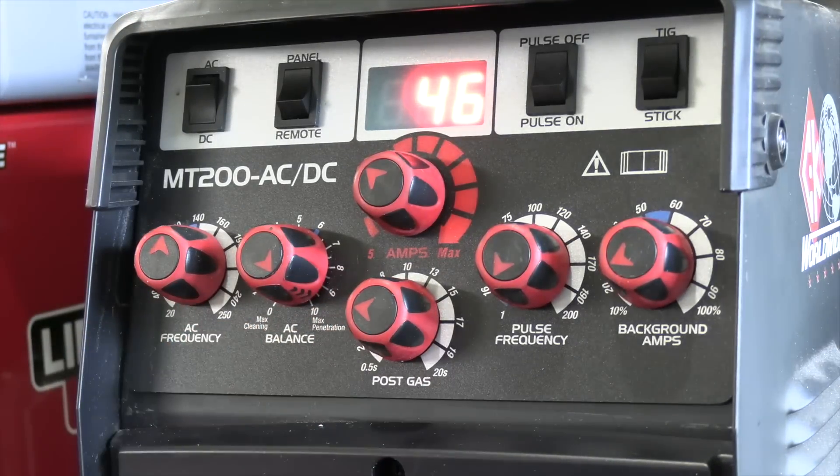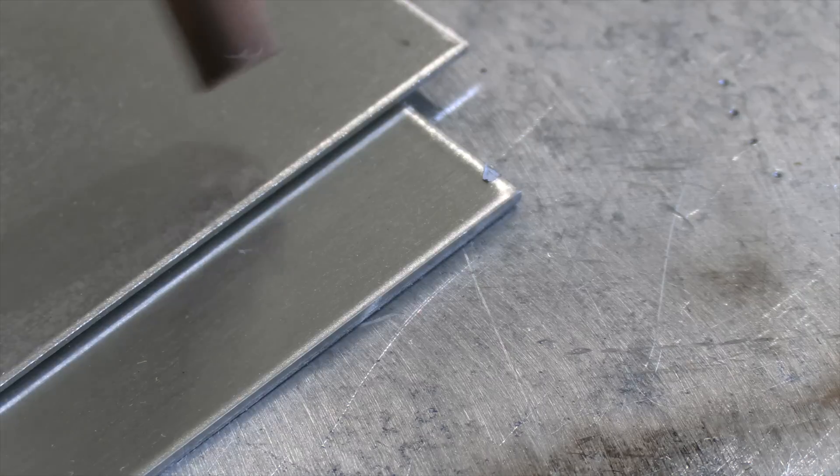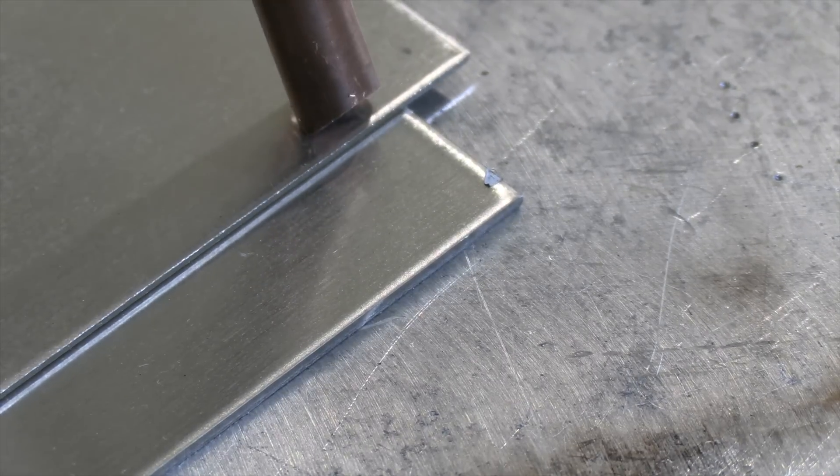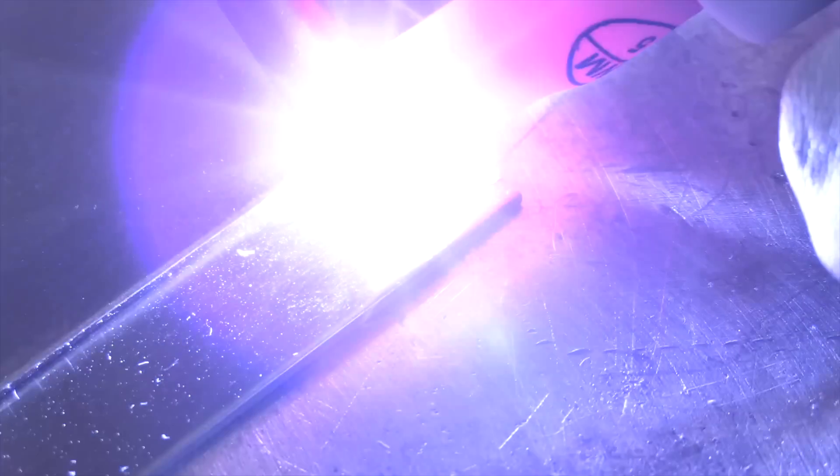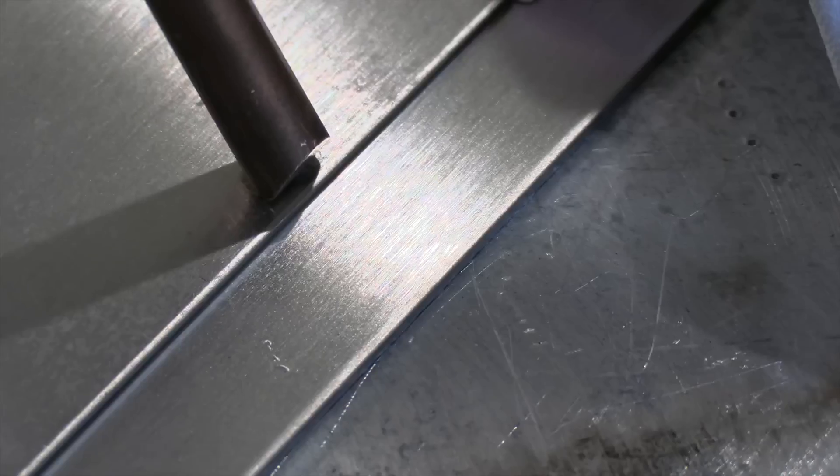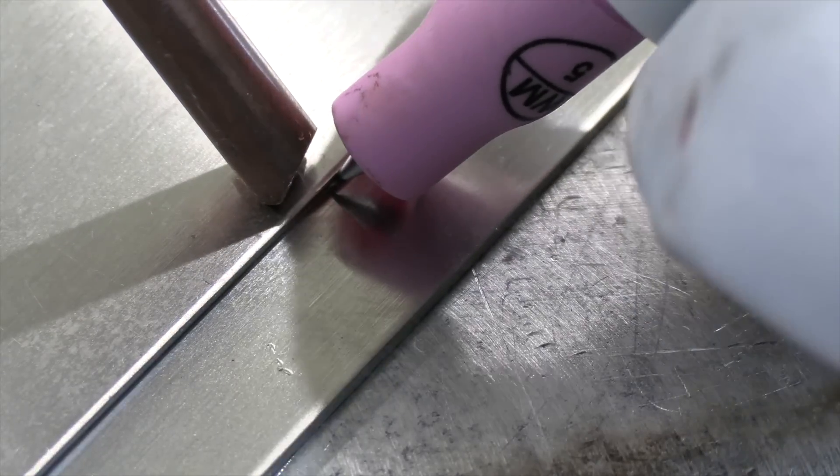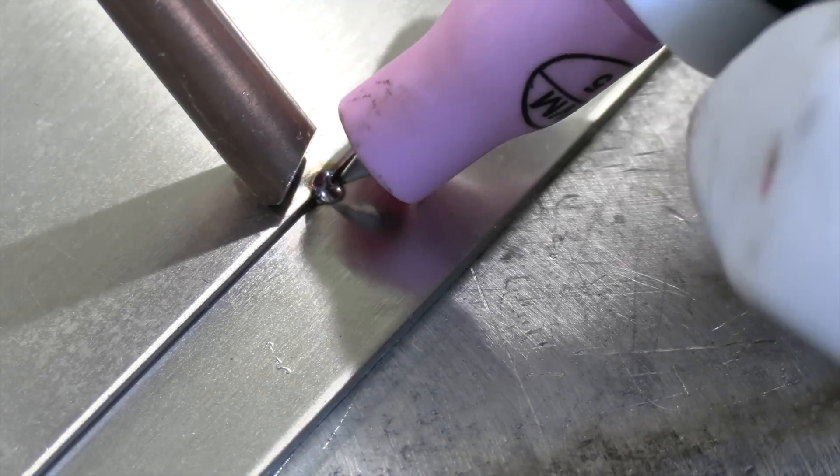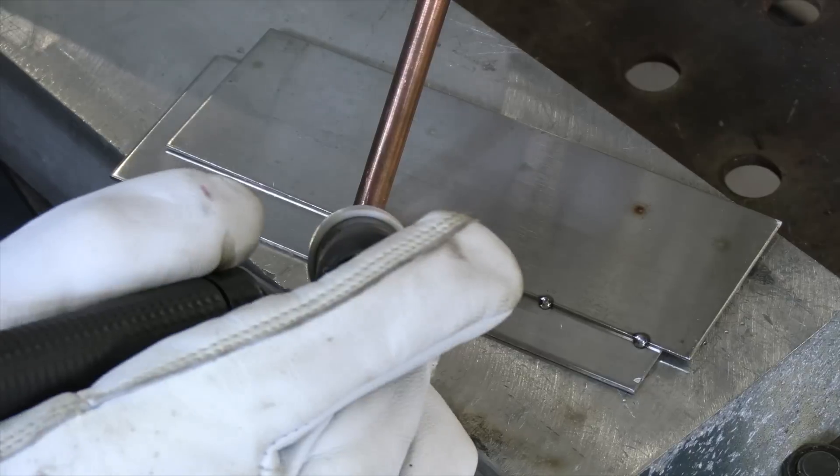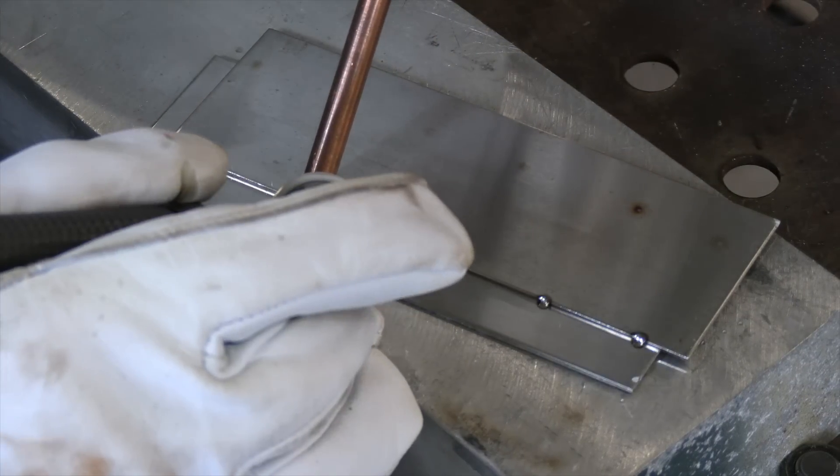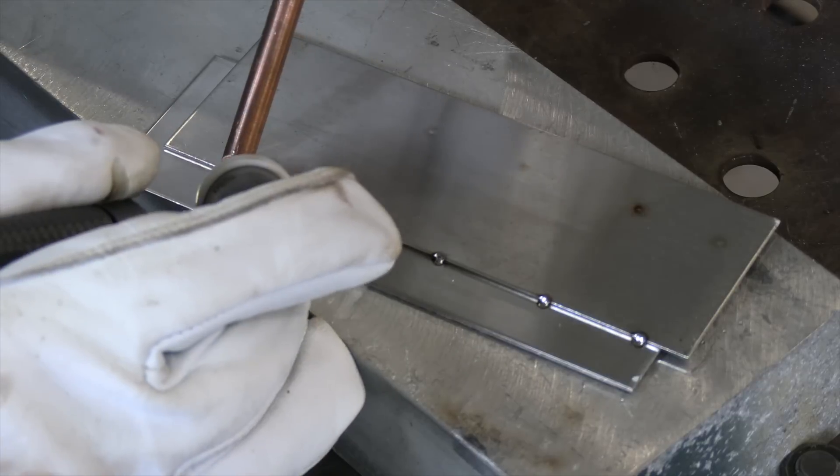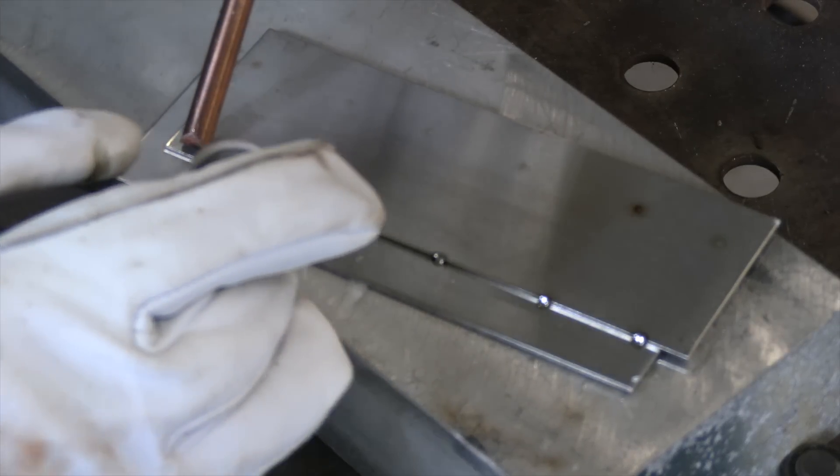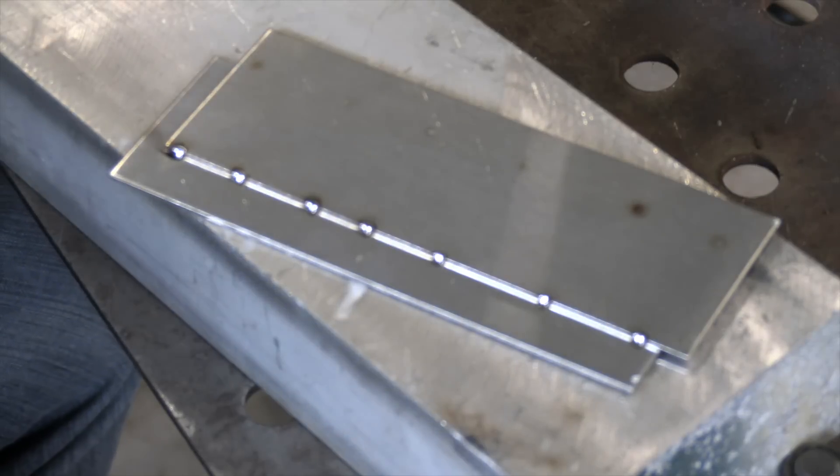I'm turning the post flow down to save some gas. 46 amps. The trick is no gap, so I'm using a little hold down tool, a copper hold down tool, right next to where I'm going to put the tack. I put a lot of pressure on that, and sometimes I even just use the cup to put pressure, but in this case I need a little bit more pressure than I want to put on a cup. You don't want any gaps when you're trying to do little fusion tacks like this with no filler metal. You're trying to make the tack a little bit smaller than the final weld will be, so you can't tell where the tack is when you're done. That's the goal anyway—doesn't always work. But real quickly here I can put a whole bunch of tacks using that little trick.